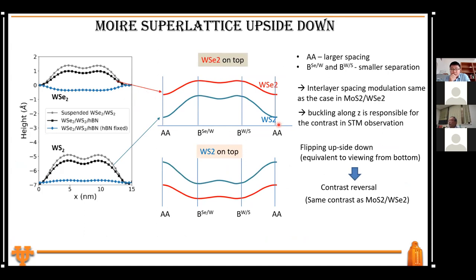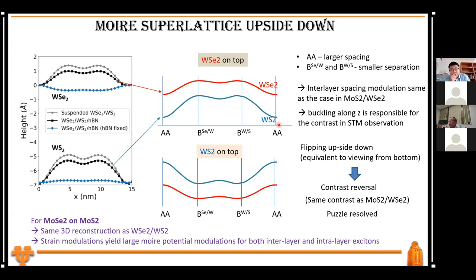And then we reproduced that strain relaxation using a simulation, and now we have incorporated the strain effect that calculates the strain, to incorporate the deformation potential. And I believe the result is that it can explain what we observe in a high moiré potential depth for the intralayer exciton. So this is sort of the case.